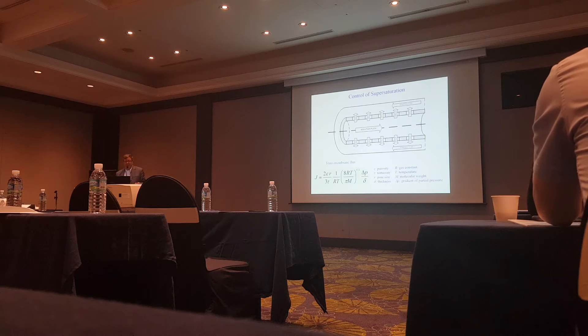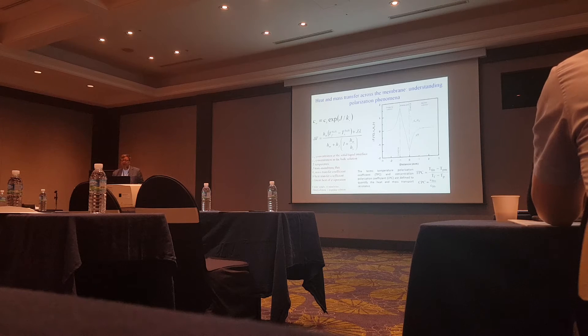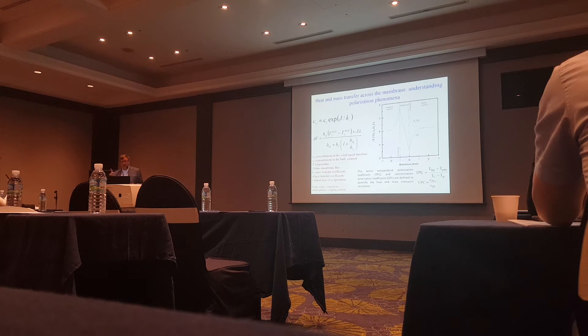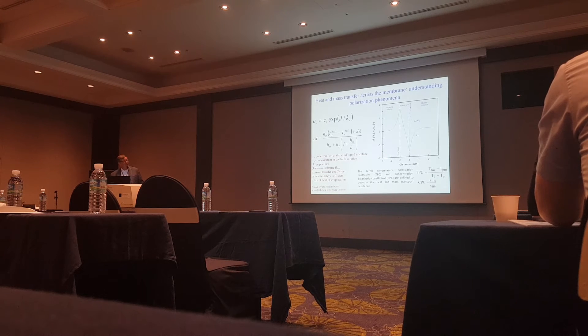In the literature you will find that the membrane — we are always using hollow fiber — is a place where each pore, assuming they are all equal and parallel, is a site where you can induce crystallization. You have a very homogeneous distribution of the metastable phase where heterogeneous nucleation is supposed to take place — very different from traditional systems. You also have to take care of concentration polarization phenomena and temperature polarization phenomena, because you can have temperature and concentration interfaces at the membrane surface that affect the system.